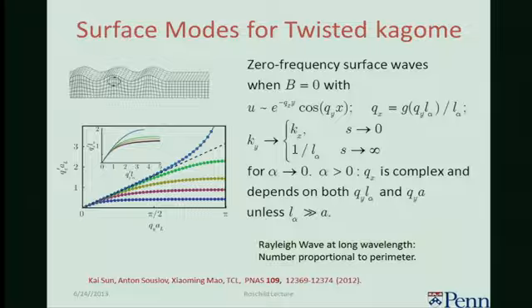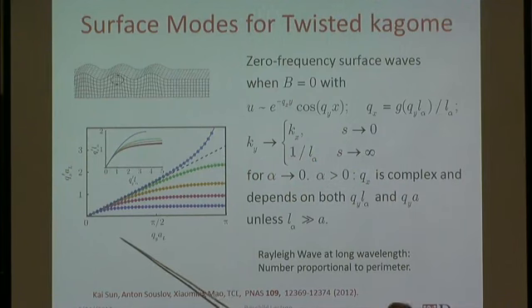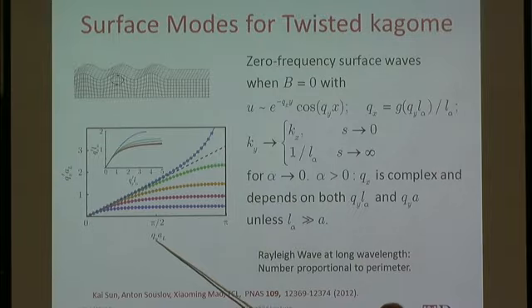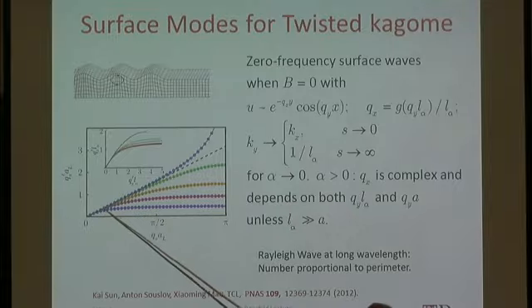Now, of course, we're not restricted to be in the hydrodynamic limit where the wavelength is long. So if I plot q prime of x, so now what I have is a surface that's parallel to the y direction, and I look at the inverse penetration depth into the x direction. The long wavelength elastic theory will tell you that q prime is exactly linear in qy. In fact, it's equal to qy. So these are both simulations and our analytic calculation, which you can do with transfer matrices. It rises linearly, and then it reaches a saturation value where qx is exactly 1 over that length, which goes as sine of theta.